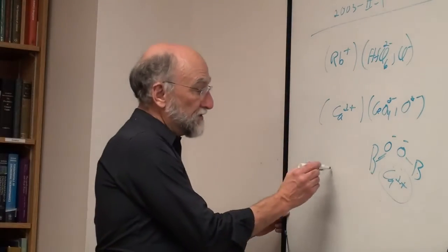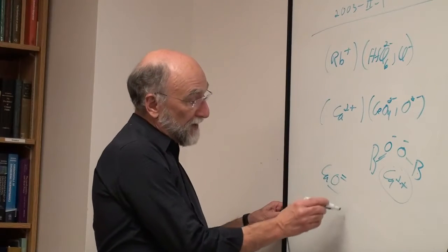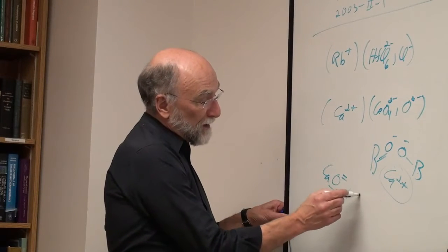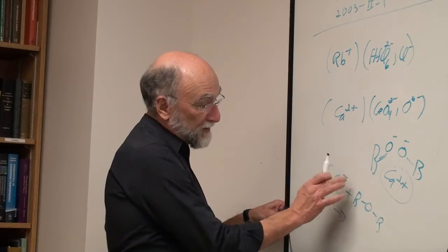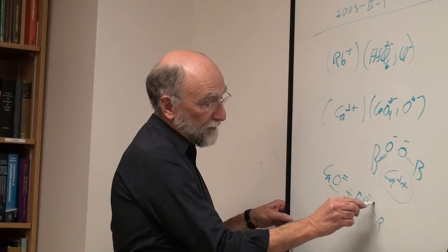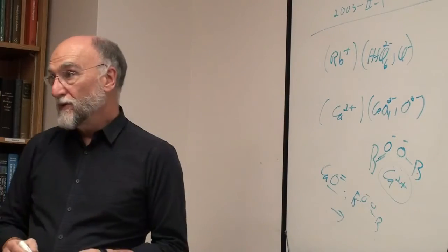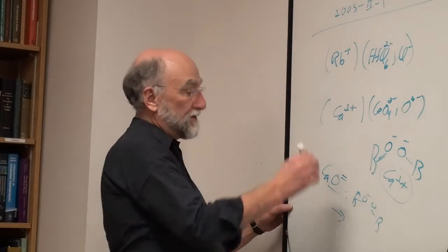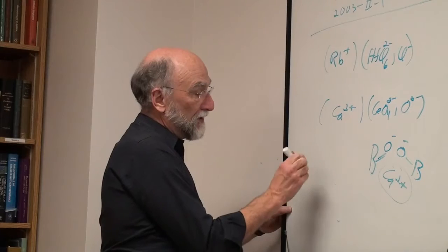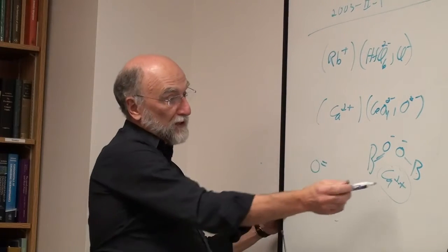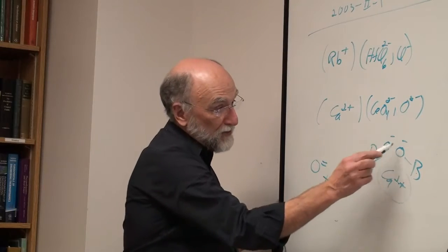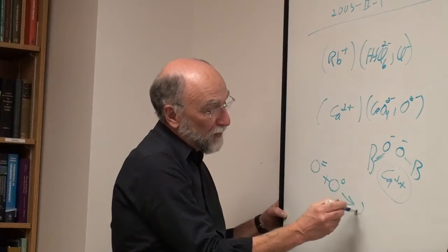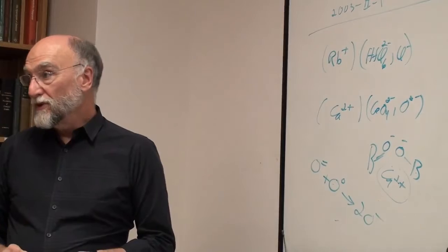The reaction being the CaO provides an oxygen ion plus then the boron oxygen boron bridge, and this breaks the bridge to form B-O-. Or it's the same thing as before. You can talk about an O2 minus, which is the oxygen ion coming from the calcium, plus an O0, which is the original oxygen bridge, forms two broken bridges.